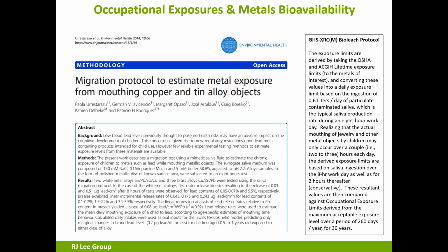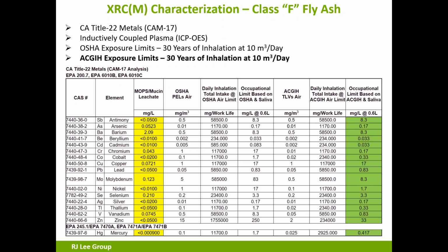So what we did is we found a study that was done for children of jewelry mouthing. And actually, as we've learned since we started doing this, this type of characterization is basically common and used in California for a lot of leachable metals. So this BioLeach protocol basically is soaking the material at body temperature with constant agitation for a certain period of time, and then analyzing the leachate. And it reflects occupational exposure over the course of 30 years. It is not based on lifetime exposure, which is what the Clean Water Act data are based on. It's based on occupational exposure, which is a big difference in years, 70 versus 30.